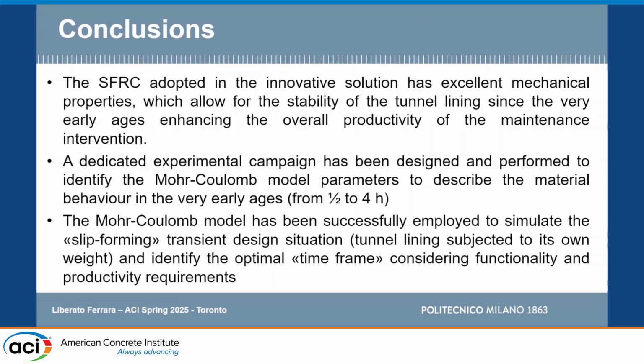So, just quickly coming to the conclusions. We have developed this 3D printing inspired self-compacting fiber reinforced concrete with very rapid strength gain, which proved an interesting solution for this tunnel retrofitting technology that we developed. Obviously, the key properties are the properties at ages going from a few hours up to 1 day, which are the critical times where you have to decide whether to advance with your slip forming technology and how safe your ongoing tunnel lining is in order to go on with the operation, because at a certain point you must also allow the crew of workers to go into the lining, and so you have to guarantee a certain level of safety.